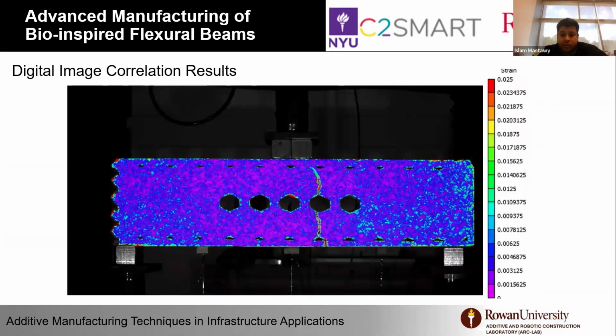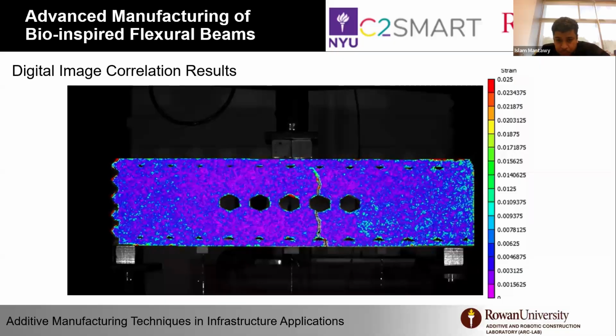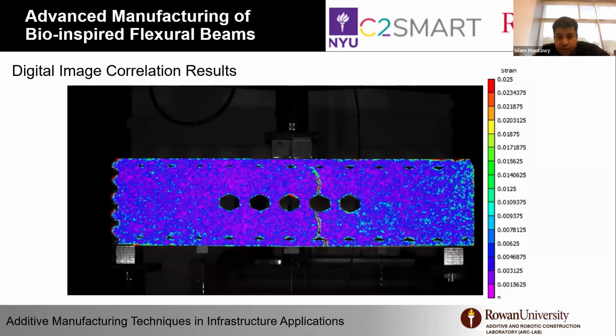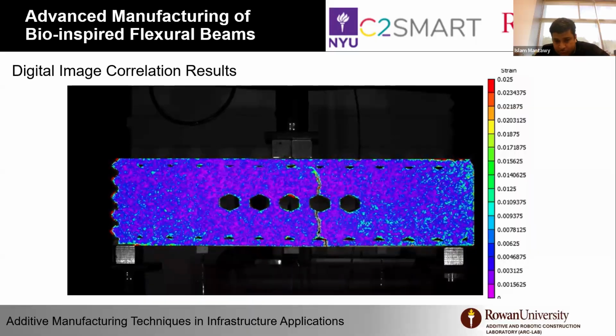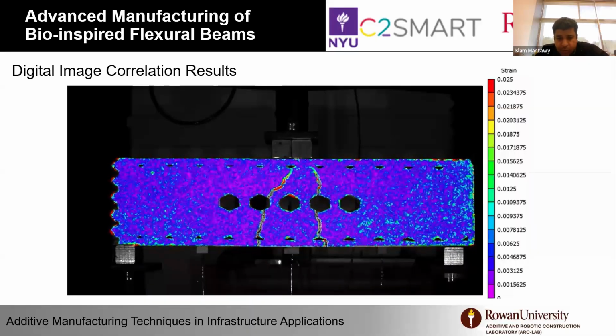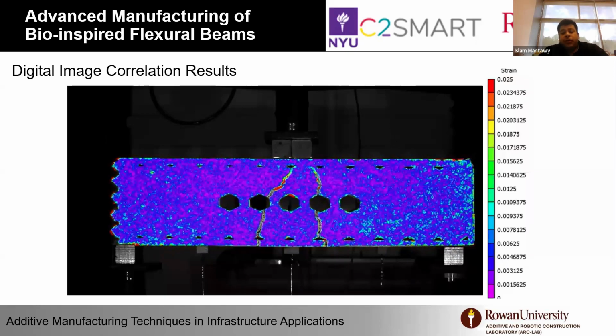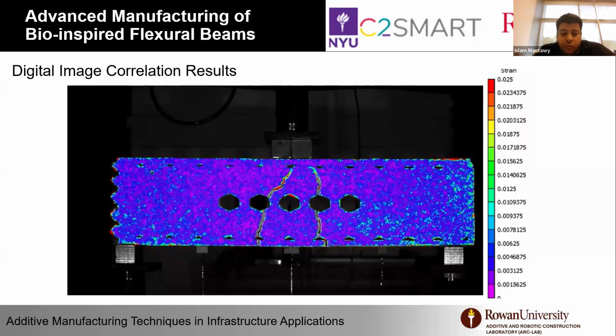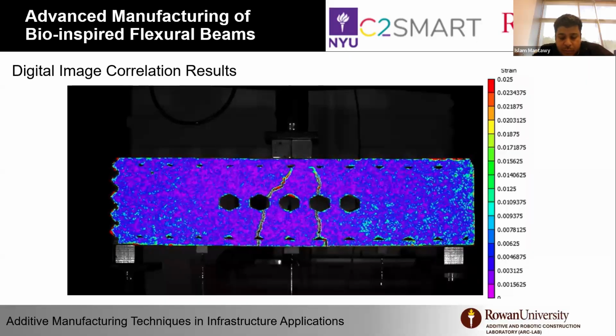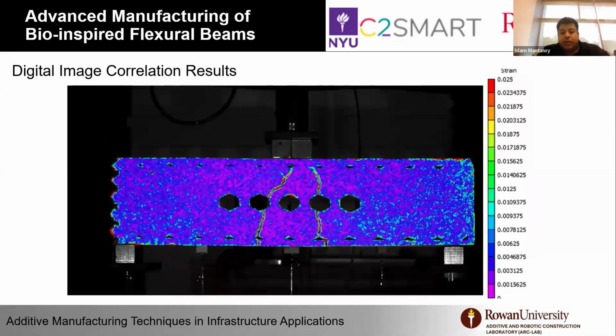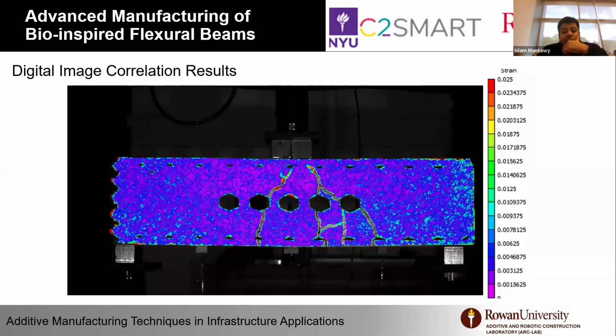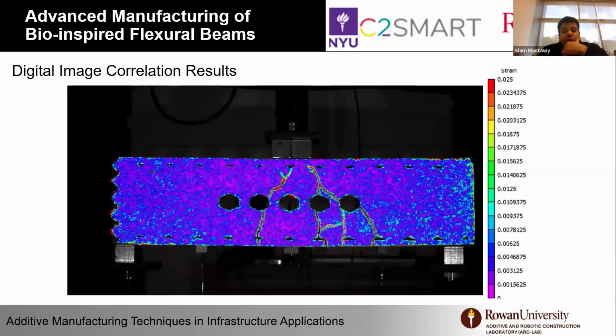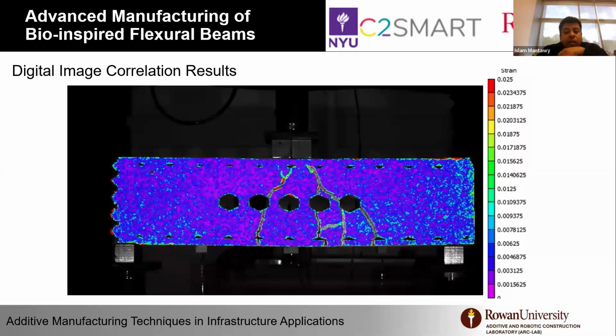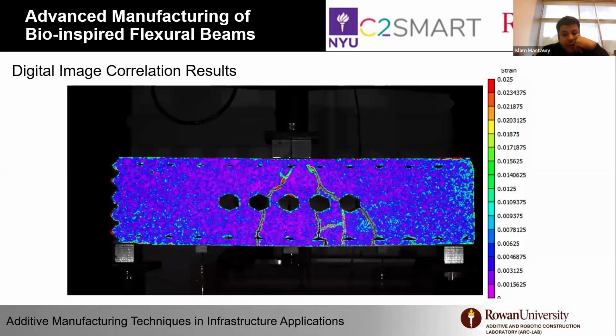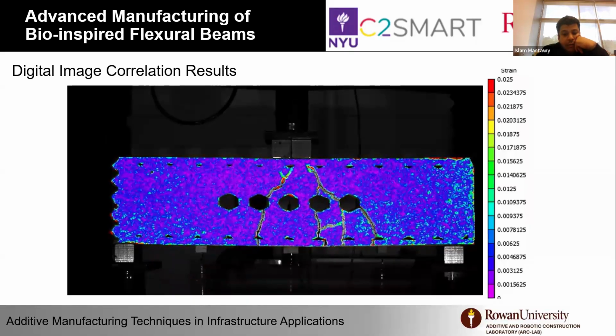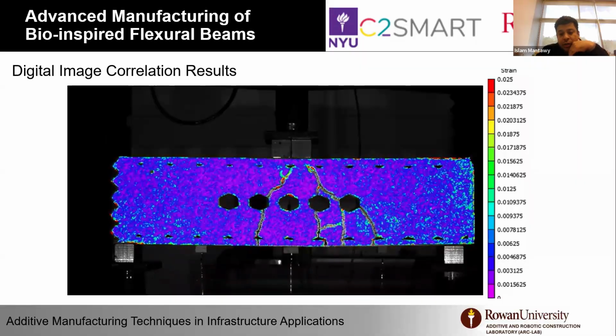So you can see here, the crack started almost near the middle, as in any regular concrete structure. We noticed that cracks are wider here because of the flexible cable that we used. So we moved to rigid reinforcement in a different iteration, which is future work that we plan to do. You can see the cracks initiating as you load the structure, and the cable is more engaged in carrying the tension force. We didn't notice any shear cracks, which verifies for us that the cable layout was sufficient to arrest the cracks at the shear zones.